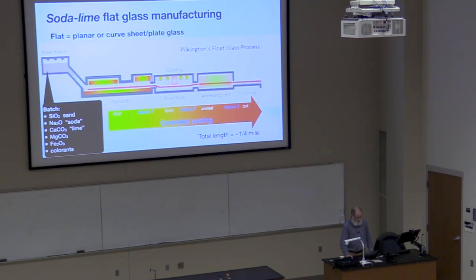As the glass flows down here, you can imagine, one, you've got to melt it all. You don't want any of the little clumps that don't melt, because those will show up in your window, right? And then there's bubbles. Sometimes water is sprayed on the batch to keep the dust down, so you're getting the water off. And then some of these materials, like these carbonates, give off CO2.